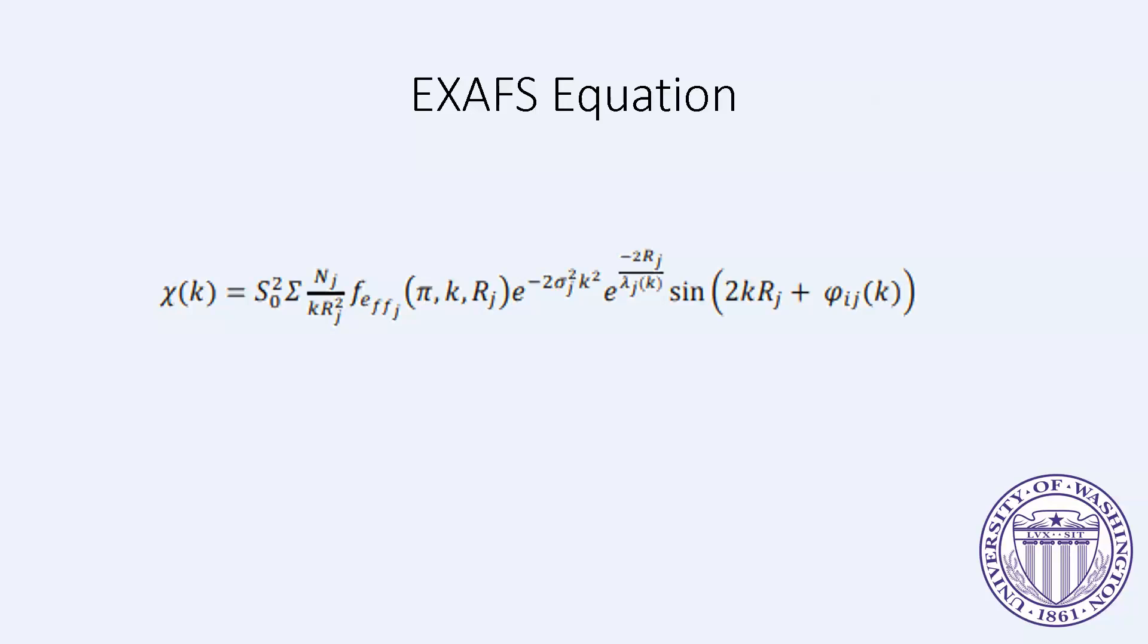Typically, the EXAFS equation is used to fit experimental data using N, E₀, R, and σ as variable parameters, usually keeping S₀² fixed. The FEFF program from the University of Washington performs curve fitting with ab initio calculated phases and amplitudes. Other software, such as the Demeter program, has been used also in EXAFS analysis.